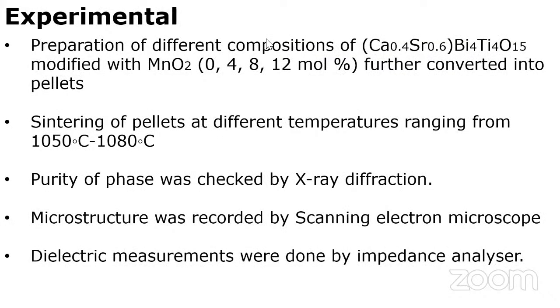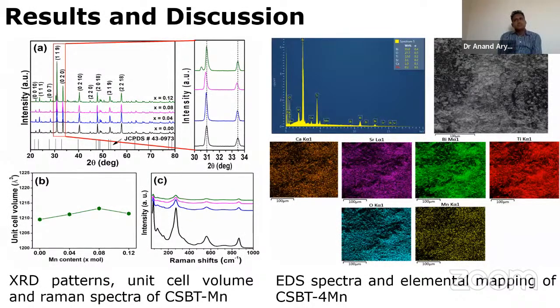Now focusing on the experimental work. Different compositions of CSBT were prepared with different percentages of MnO2. The powders were converted into pellets. The pellets were sintered at different temperatures ranging from 1050 to 1080 degrees Celsius. XRD was done on the pellets to check the purity of the phase. SEM was done to check the microstructural properties. Finally, dielectric measurements were done using the impedance analyzer, where we analyzed the different electrical properties and decided the better composition. Now moving towards the results and discussion.